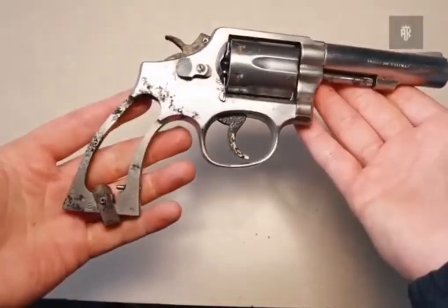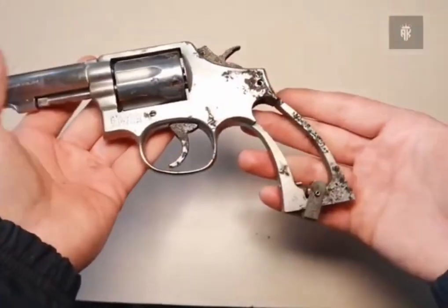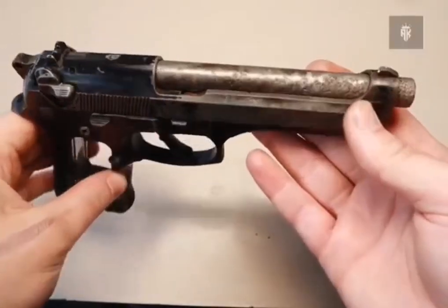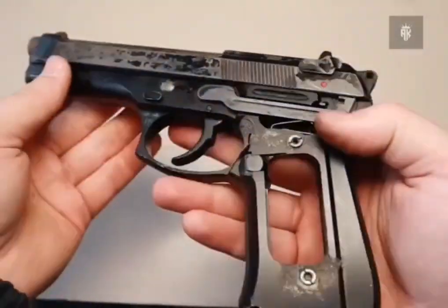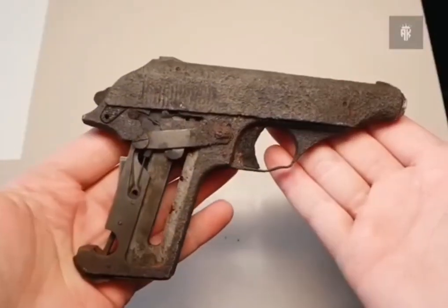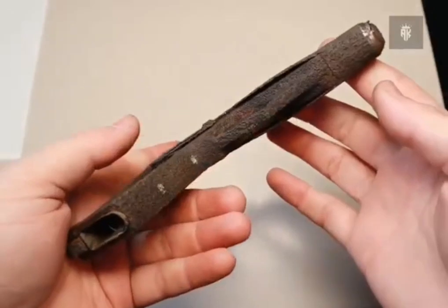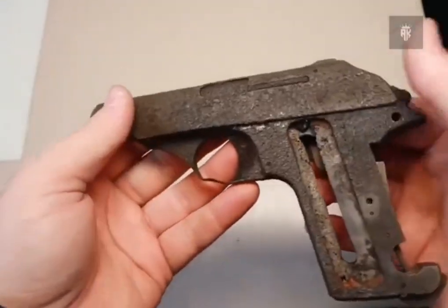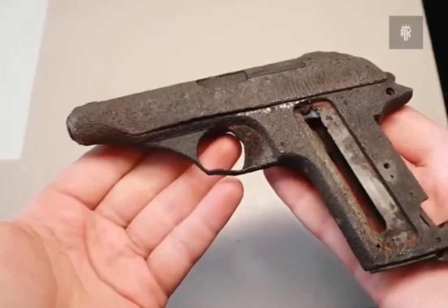At this point, both the Beretta and Smith & Wesson are clean and reassembled. It's worth repeating that I didn't make any attempt at doing a restoration on these. All I had to do was seeing if they could be operated and shot. For the Bernardelli, this was certainly not the case. After days of work, I managed to get rid of most of the accessible corrosion products, but there are still enough in the crevices that keep the parts seized up.